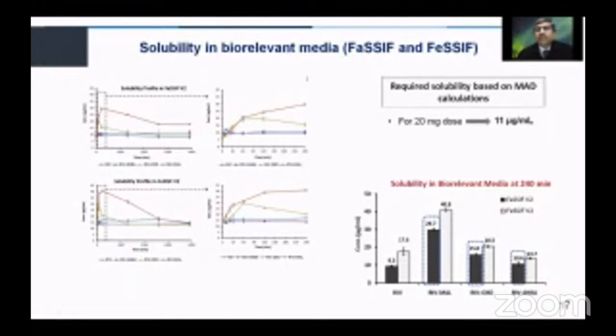The solubility of the co-crystals were evaluated in biorelevant media, that is the fasted and the fed medium. So in this particular bar chart, we have shown the values of solubility that were obtained. So this is the solubility that was obtained by rivaroxaban in the fasted medium and in the fed medium. This is with the malonic acid co-crystal, this is with the oxalic acid, and this is with 4-HBA. As you can see, 4-HBA did not lead to any significant improvement in the solubility. Hence, it would not be an ideal candidate for taking further. However, we kept on evaluating it for other parameters as well.